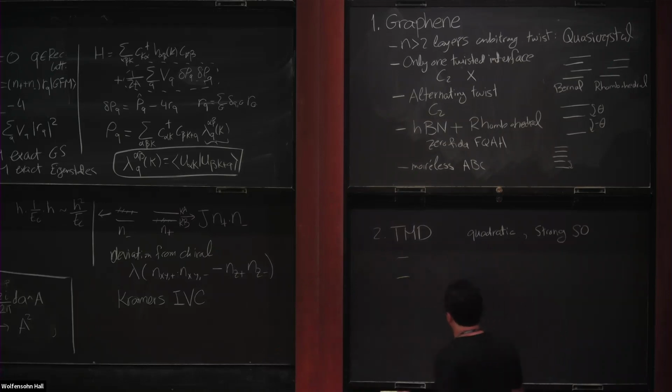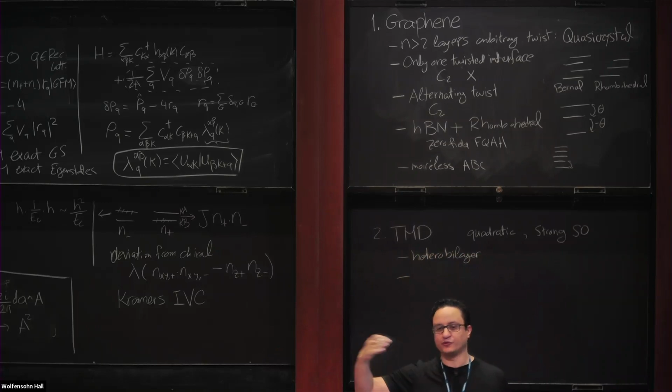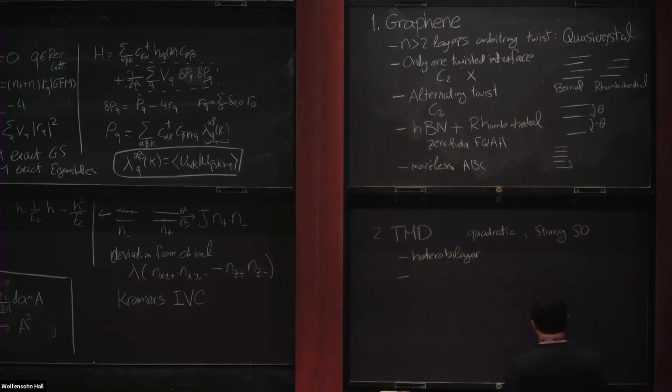One is the heterobilayer, where you take two different TMDs with slightly different lattice constants, so you get the moire from the mismatch of the lattice constants. And usually these lead to trivial bands, so bands that don't have topology and don't have a Wannier obstruction. So for these systems, we can run the usual story: find Wannier functions and find an effective lattice model. So these systems actually describe some triangular lattice Hubbard model, at least the most common ones.